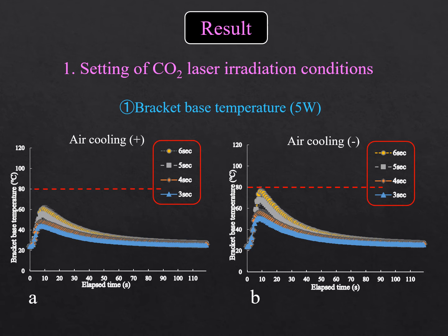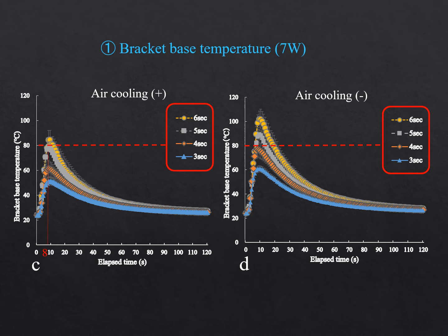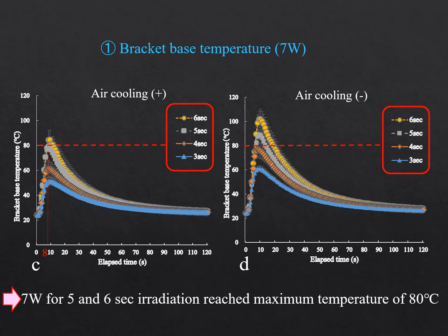The results are as follows. The bracket base temperature was measured during irradiation in 5 watts for 3 to 6 seconds irradiation, as shown in the slide. The maximum temperature did not reach 80 degrees regardless of the presence or absence of air cooling. With 7 watts irradiation, the maximum temperature reached 80 degrees or higher after irradiation for 5 and 6 seconds with or without air cooling. Therefore, both irradiation times were considered to be appropriate.